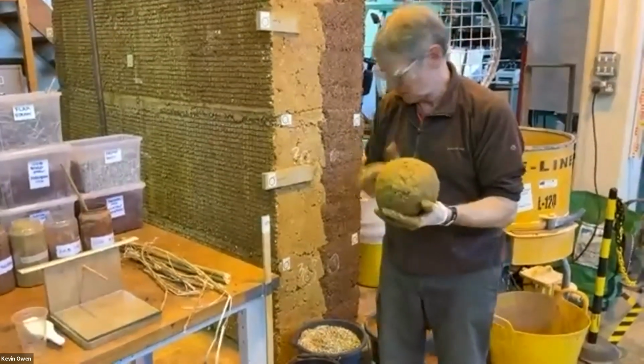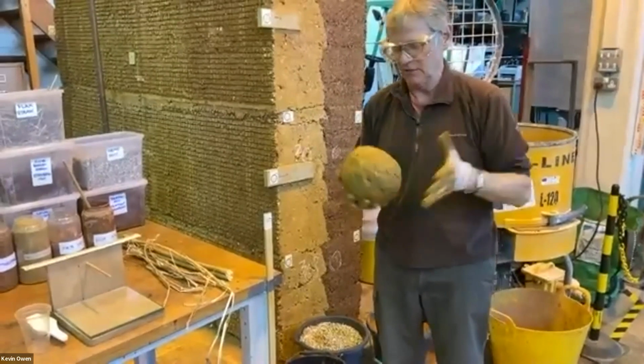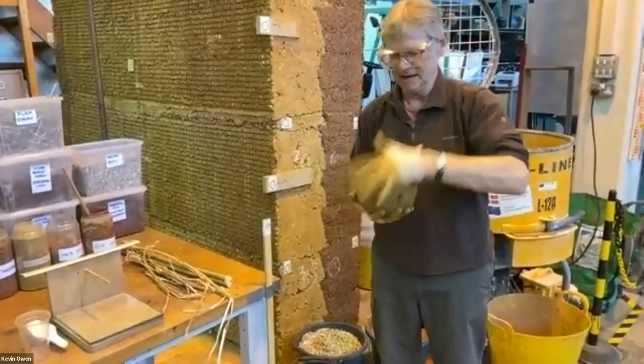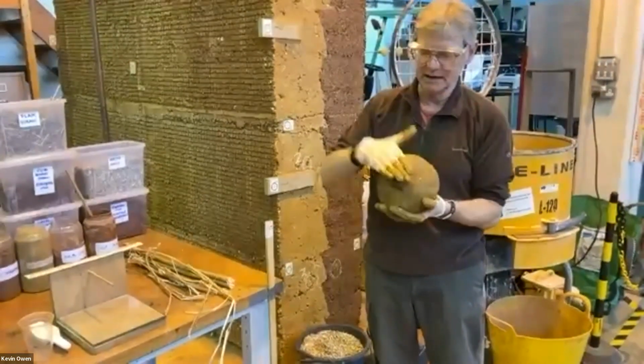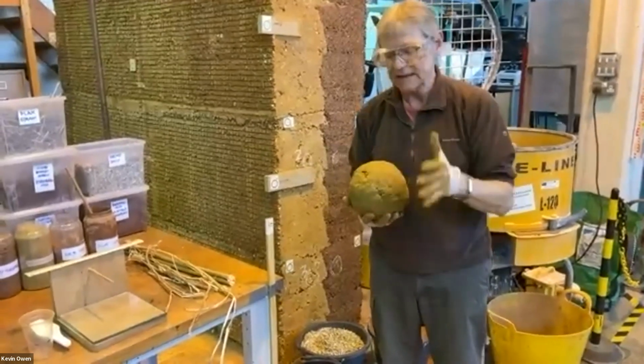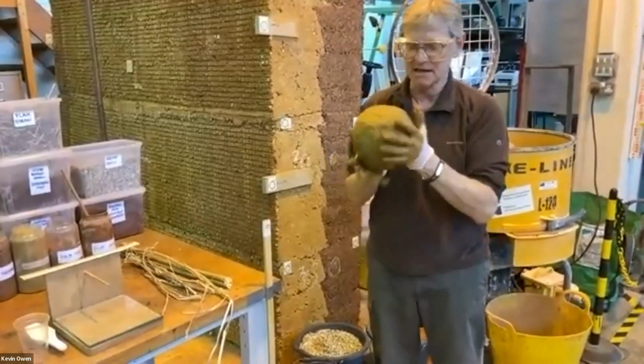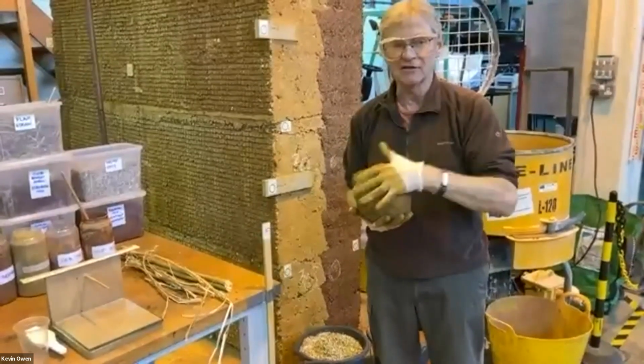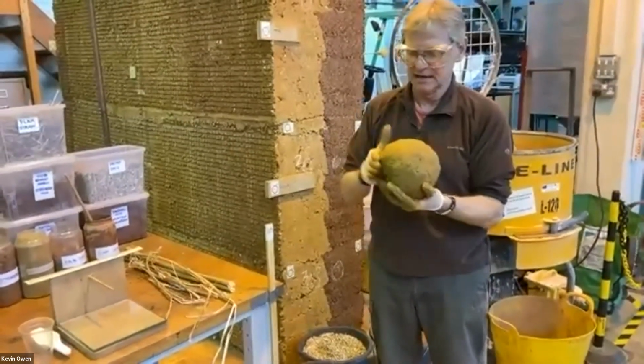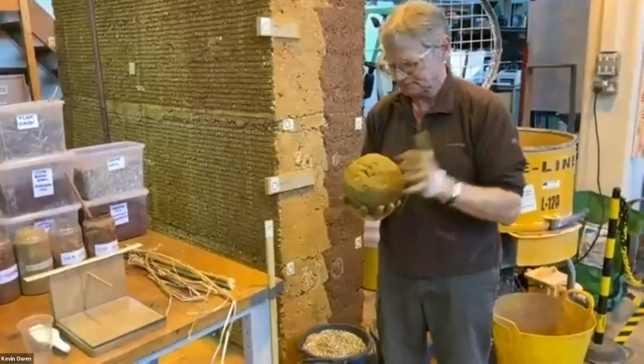So this is a 2-litre container, and we put inside there the cob mix that's already got the fibre in it. So we already know what the mixture is for that, and in this case it's a 2.5% fibre mixed with the weight of dry material.